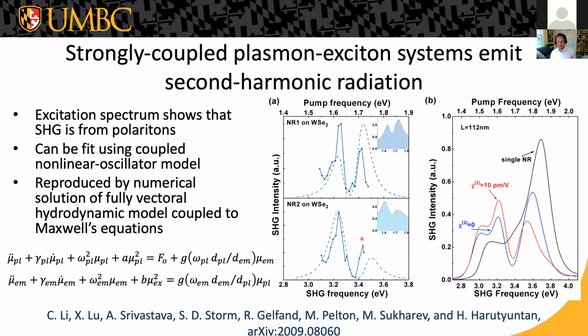And we can understand this again in a classical sense. The strong coupling is really not a quantum mechanical phenomenon. It's really something that you can understand very well classically. So the simplest way to do it is just to take our coupled harmonic oscillator model that we already had and just add second order nonlinear terms, add an anharmonic term to each of the oscillators. So now we have coupled anharmonic oscillators, and the usual kind of perturbation analysis gives us the second harmonic intensity as a function of the fundamental frequency. You can see that we reproduce pretty well the experimental spectrum that was measured.